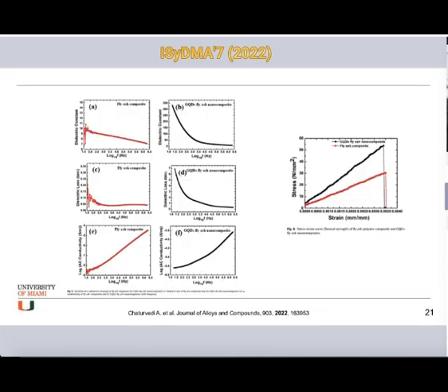For parts A and B, the figure shows the variation of dielectric constant with frequency for the polymer. We can see that the dielectric constant decreases with the increase of frequency. This is due to the overall contribution of dielectric polarization, and that includes what I mentioned for the last published work: electronic, dipolar, ionic polarization and space charge polarization too.